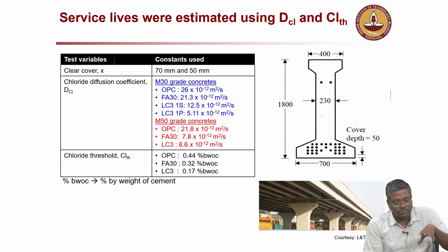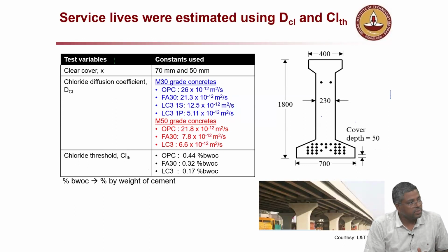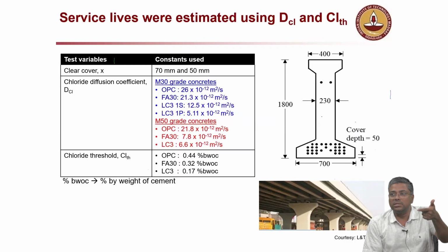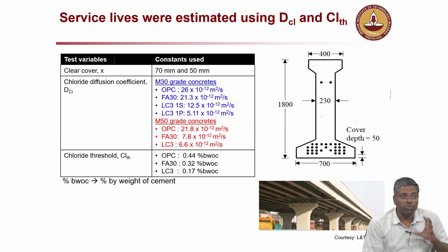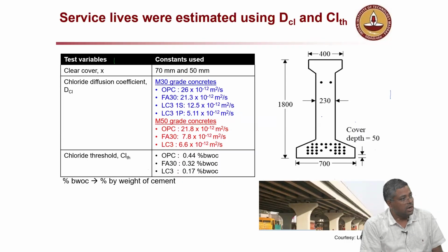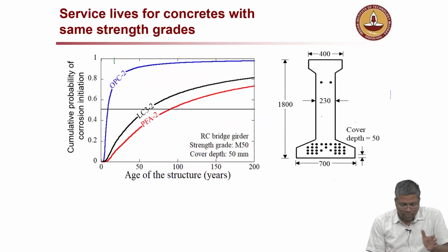So here you can see cover depth is one parameter, diffusion coefficient, which is the speed by which chlorides penetrate. For different types of concretes, you can see different numbers. And then boundary condition, which is chloride threshold, how much chloride you need for the steel to start corroding. So based on this, we estimated service life for 3 different cases. You can see OPC, 3 different mix designs.